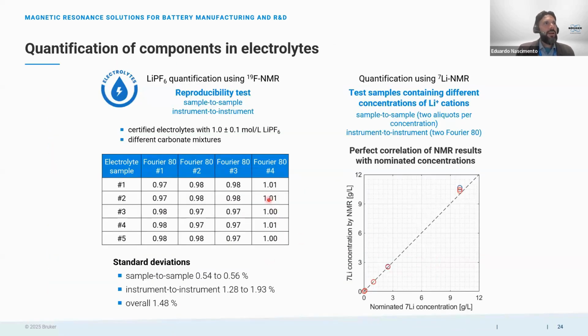So as I said in the beginning, here I am presenting some reproducibility results. If you look in the column, we have here the same sample that was prepared in five different tubes. So you can see that for one system, the sample-to-sample variation is quite low, something around 0.5%. The same sample, if you prepare 4 samples and analyze that with 4 different instruments, so now we have instrument to instrument variation, which can be something around 1.28 to 1.93. So the overall variation here is estimated at 1.5%. So this is a quite reproducible method.